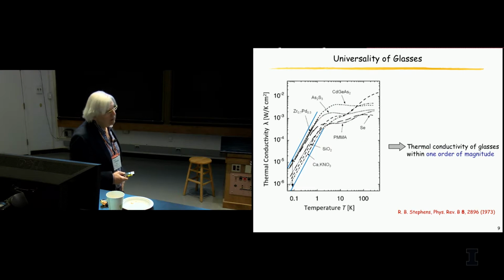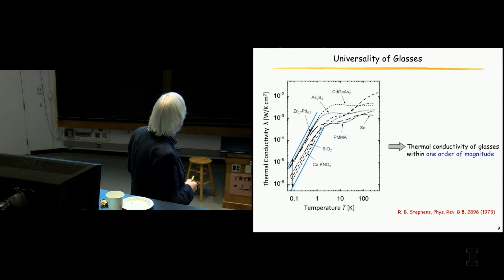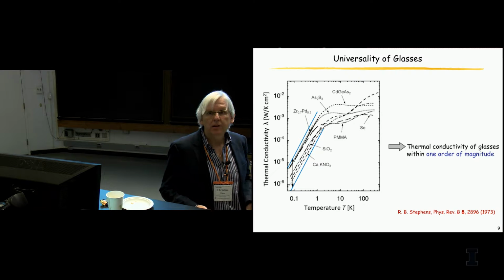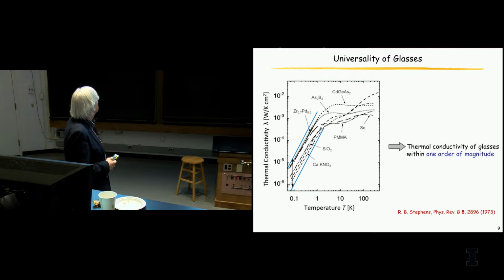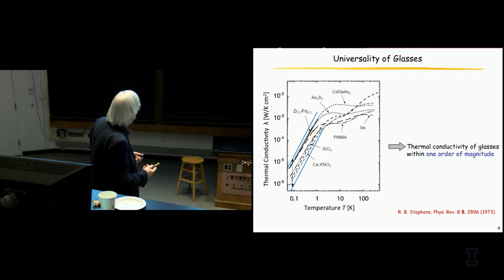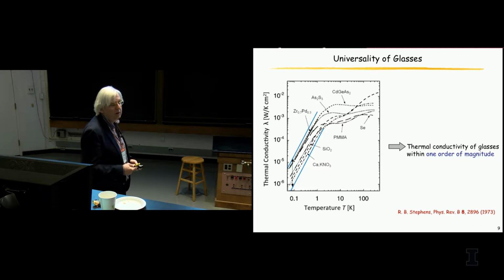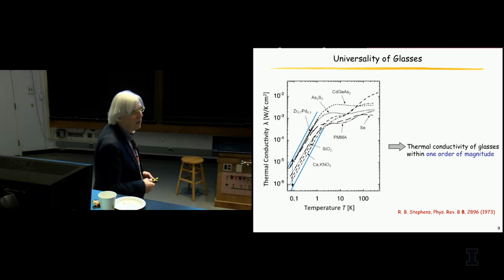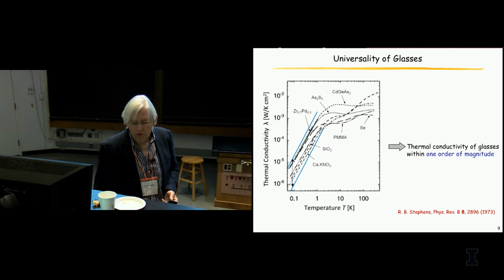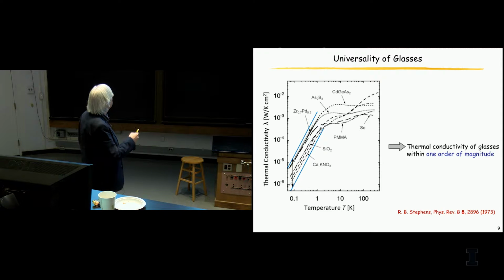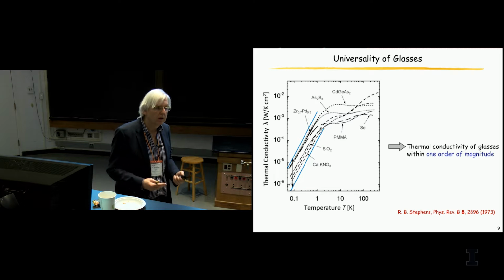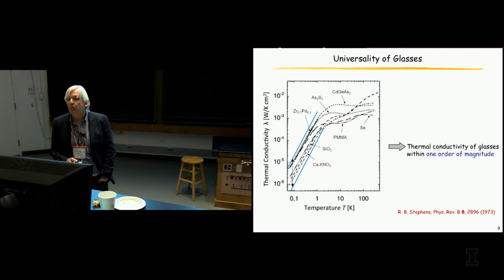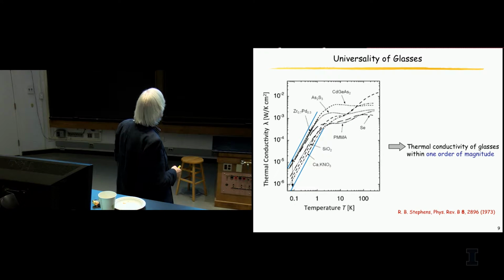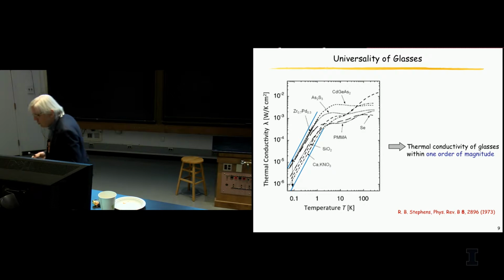Now, the universality is a fact which was seen here in Urbana by Andy Anderson and others. It's the observation that no matter what glass you cool down, whether it's a polymer, a strongly bonded structural glass, or metallic glass, you find that in the regime, at lowest temperatures at least, the properties are almost identical. Not only that it's a T squared, but also the prefactor, the coupling to the phonons, is roughly the same, within an order of magnitude. And that's very striking. You can choose whatever composition, you will always find this. So there must be a reason behind that.